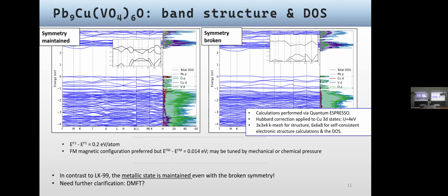So in order to explain the first results, I need to go back and say that, of course, all those complicated theories are fine, but first, in order to have any superconductivity, you probably need to have a metal state. Your sample has to be a metal in the normal state, at least. And therefore, the preliminary step considered in this search was to look for stable metallicity in the compound under consideration.